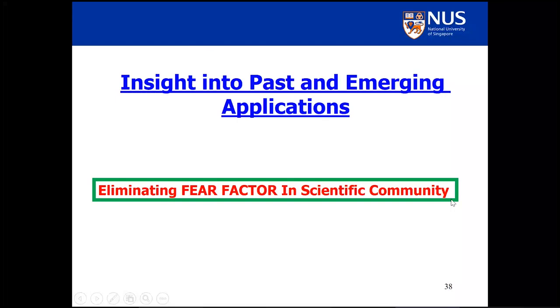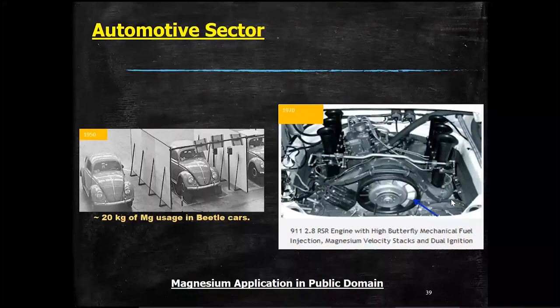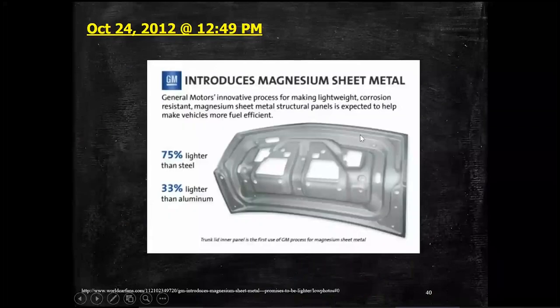Now, to further strengthen your understanding of magnesium, because some people still say, hey, magnesium can burn very fast. But that's not the case. It's a very big misunderstanding between the research community. As I've shown in this image on the left-hand side, the famous Beetle car used 20 kg of magnesium. It was used way back in 1970 in the engine component. Now, these are the hot areas, no issues. General Motors put the magnesium in the boot area. The selling point is very simple, 75% lighter than steel and 33% lighter than aluminum.